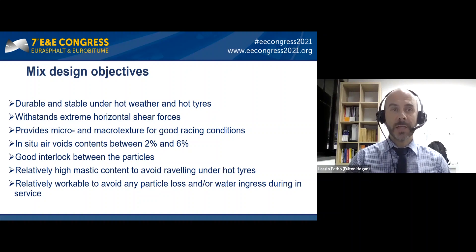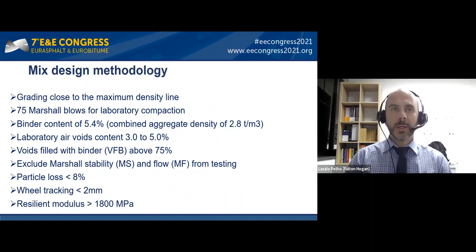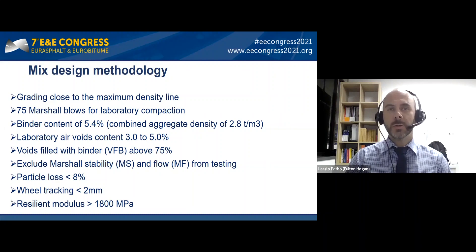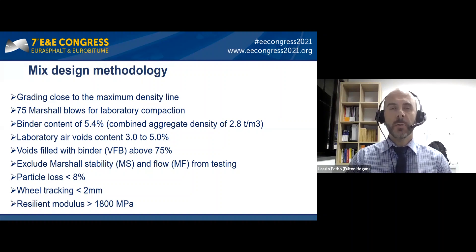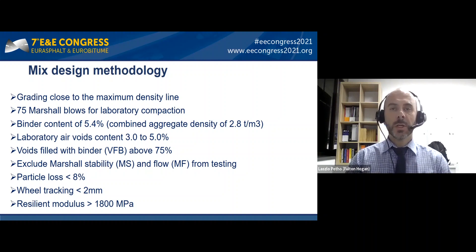With a relatively high mastic content, we had to make sure the mix was workable so we could compact it to a low air void. Our mix design methodology used the volumetric part alongside performance-based and performance-related testing. For performance testing, we used particle loss, tracking, and resilient modulus to provide upfront knowledge about the in-situ performance of the mix.